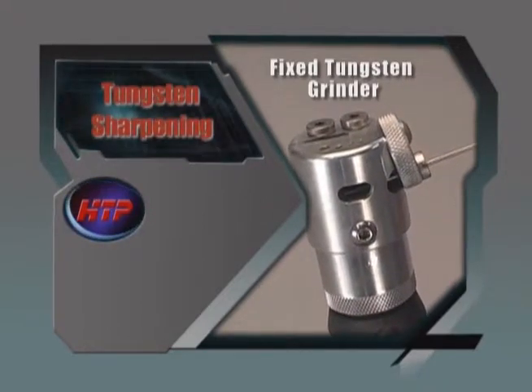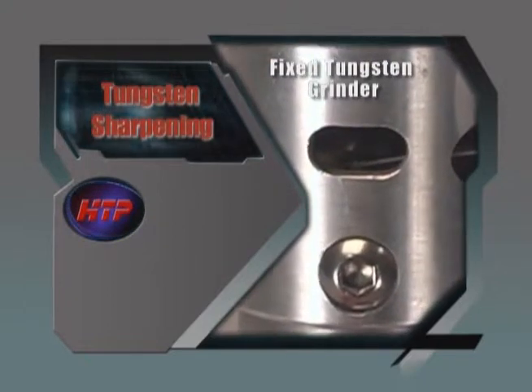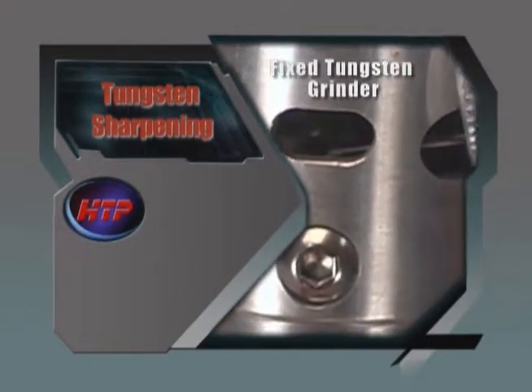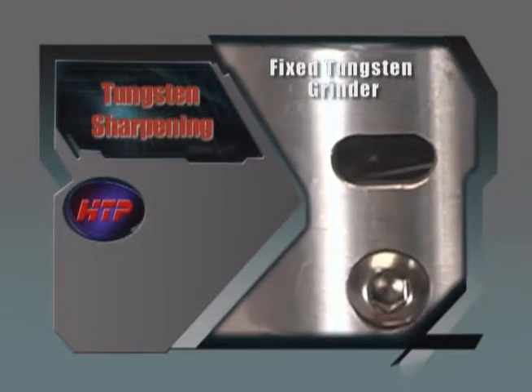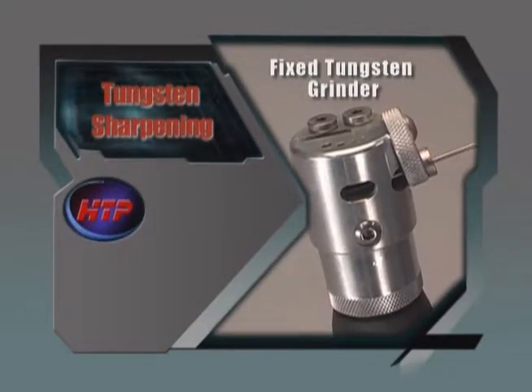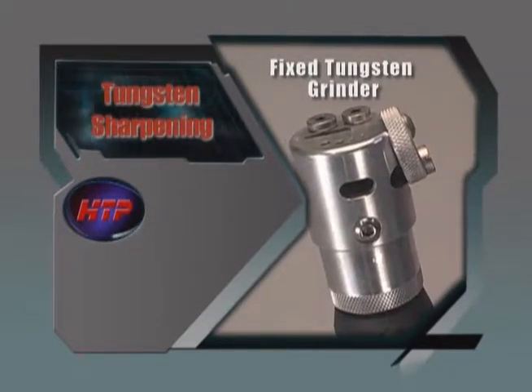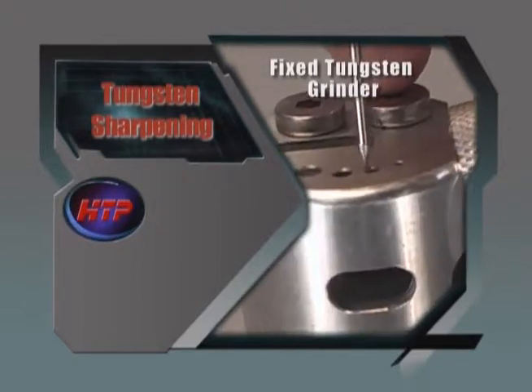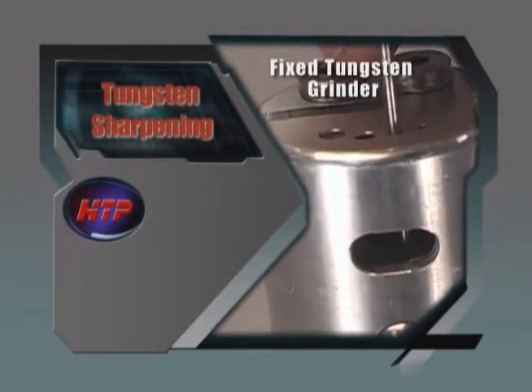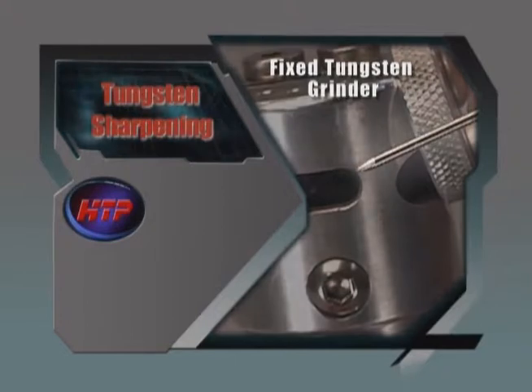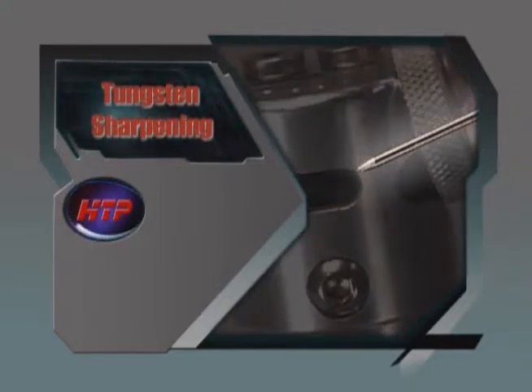When sharpening the tungsten, the taper length should be 2 to 3 times the diameter of the tungsten. You can also use the tungsten grinder to flat spot the tungsten, which is removing the sharp point on the end of the tungsten to prevent it from spitting into the weld.